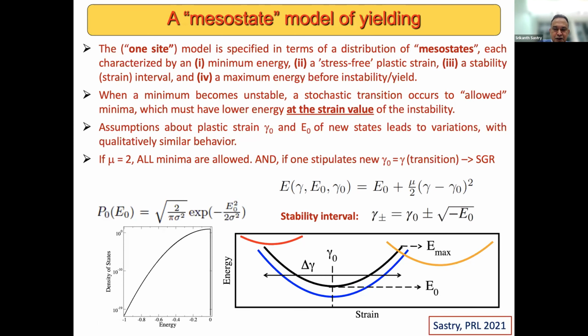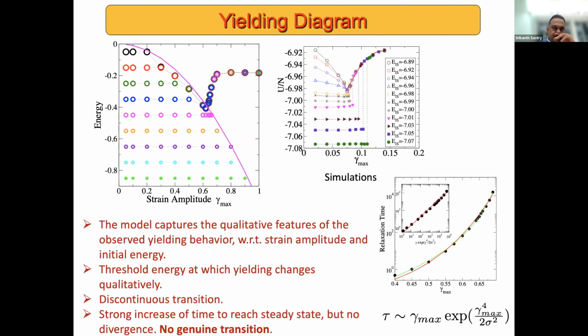Okay, so with these, one can then look at the kind of behavior that emerges, and the specific thing that I show here is to start with minima of different depths and ask, if I apply shear deformation of a certain amplitude, what happens after some large number of cycles of such deformations have been applied. The big left graph shows the final energies that I get after, I think in this case, 1,000 cycles of shear have been applied. And what one sees in quite a striking way is that this yielding diagram looks very similar to what one finds in computer simulations.